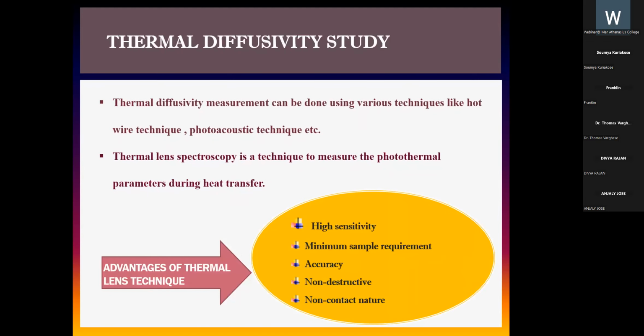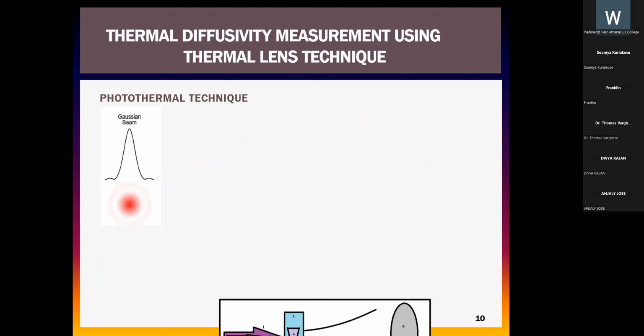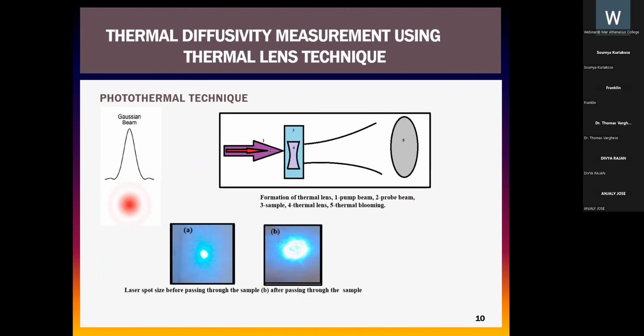Thermal diffusivity of a nanofluid can be measured using different techniques, of which thermal lens is one of the most advantageous for measuring the photothermal parameters during heat transfer. It is a highly sensitive, minimum sample required, accurate, non-contact, and non-destructive technique. Lasers make it possible to observe and understand certain phenomena which were otherwise not feasible using ordinary source of light.